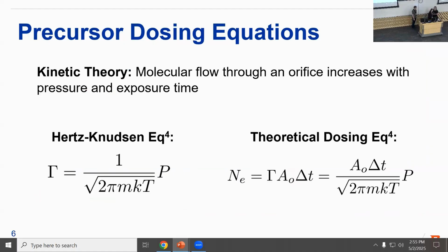All right, to dose the precursor molecules into a UHV chamber, a pneumatic valve will be open for a short dose time of delta T. Molecules emitted from the valve can be calculated based on the flux of the precursor molecules against the orifice of the valve and the dose time. So according to kinetic molecular theory, the impingement rate of molecules in a gas striking a surface is given by the Hertz-Knudsen equation on your left. M is the molecular mass, K is the Boltzmann constant, T is temperature, and P is pressure.